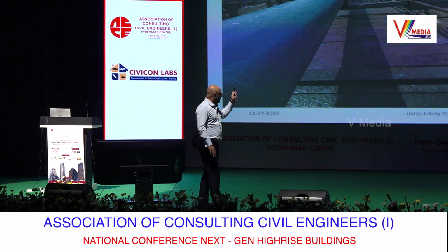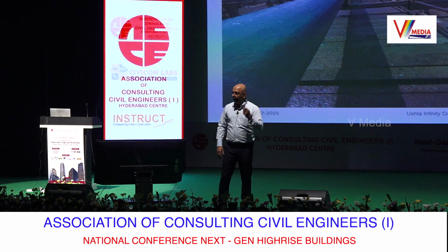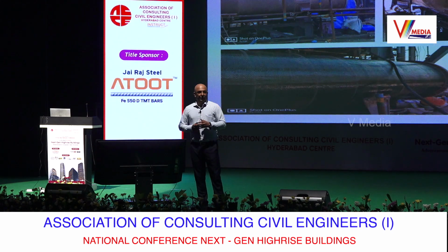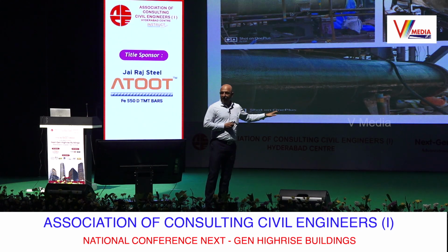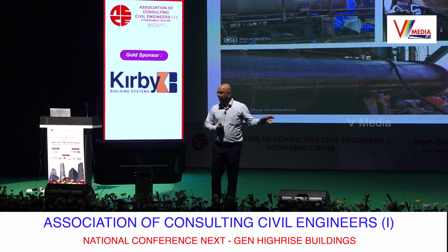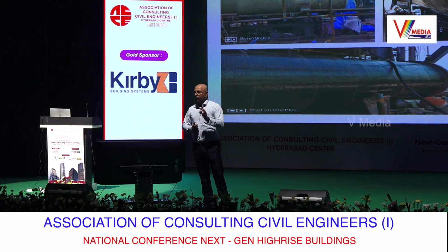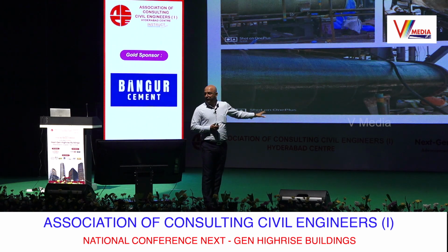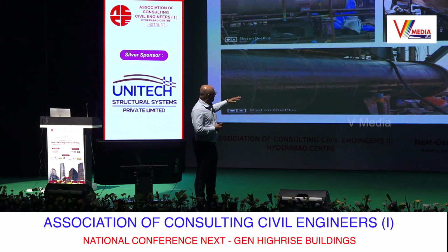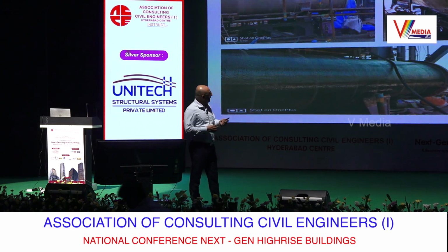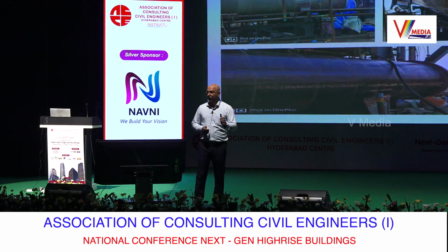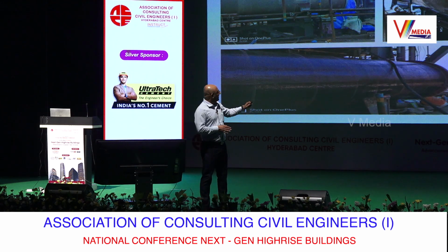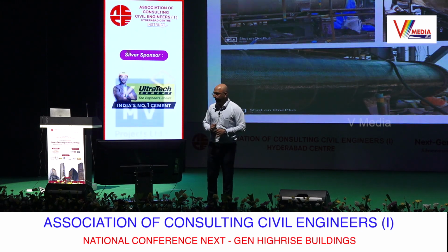Okay. So when we did this, the next question we were given is that we have a heat exchanger tube which is damaged. Can we do it? The challenge here is the temperature. The resins which we used in that were only resistant to 120 degrees Celsius, whereas here, the resins we developed were up to 260 degrees. So the family of the resin was changed, and similarly this heat exchanger tube also was repaired in record time of 7 days during their annual shutdown. Otherwise, to change this entire thing would have taken them at least 1.5 months.